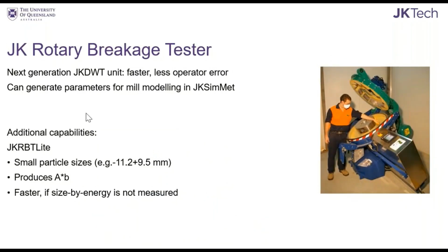Obviously. The other test that we use as well is associated with the JK Rotary Breakage Tester. This was developed as a replacement for the traditional drop weight tester unit. It's a lot faster, has less operator error, and is generally cheaper to do as well.